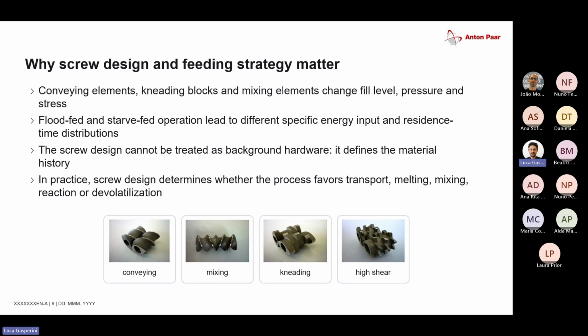So some of the parts include conveying units, which simply transport the material along the liner. We do have regular mixing units. You can see the difference in the angle. Then we have these kneading blocks, more or less used for distributive mixing, and these high shear cogwheel-like elements, which are more for dispersive mixing. Sorry, mixed it up. The whole screw configuration in a compounder determines the whole thermomechanical history of your material.